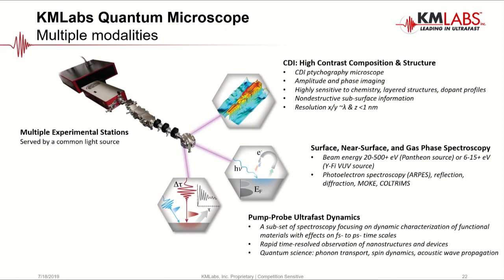And this ranges from imaging to complement what we already have in terms of visible light microscopy and electron microscopy and AFM, but we're adding some new contrast and new sensitivity to it. We're doing some interesting things in spectroscopy, where we have very strong interactions of photons with material in this energy range. Remember, think back to that periodic table I showed again, where we have a lot of edges and a lot of interesting chemistry that we can probe in the tens to few hundred eV range. And because we're using an ultrafast pulsed laser source, we can really look at the dynamic effects dictating the behavior of materials on very, very small nano and quantum length scales. So we can look at chemical or electronic or magnetic or thermal or even mechanical property effects down at these length scales that are really tough to see any other way.